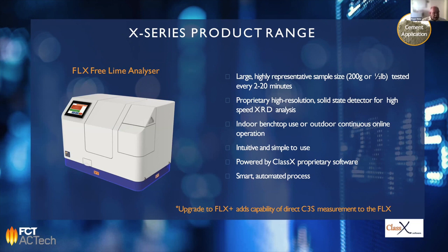For those that are not very familiar with the two different techniques, with XRF, you measure elements. With XRD, you measure mineral phases. One good example to illustrate it a little bit is if you take a piece of coal and a diamond and you do XRF, you will find out that both are built based on carbon. But if you look at the mineralogy, so the XRD signal, you see a different structure. And the structure is usually directly depending on or predicting the properties of the material. Therefore, mainly after the kiln, you look more at the properties, and there XRD has a high added value.